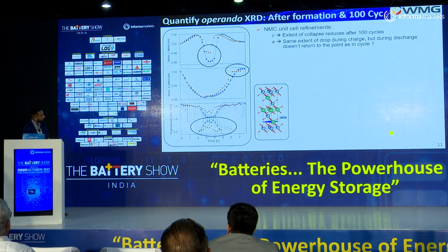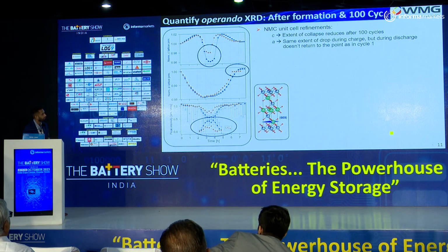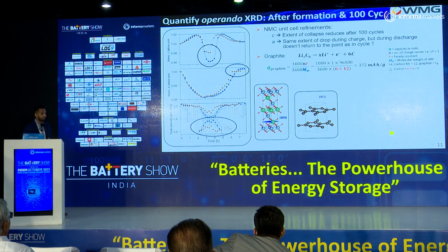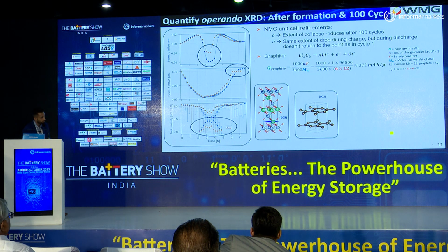So this technique allows us to fully understand where this might be arising from. Now, if we go into the mathematical equations of what our capacities are, we can see here with the graphite calculation that our calculated theoretical capacity is 372 milliamp hours per gram. Using this same equation, we can then calculate what our theoretical capacities of our cathode materials are.